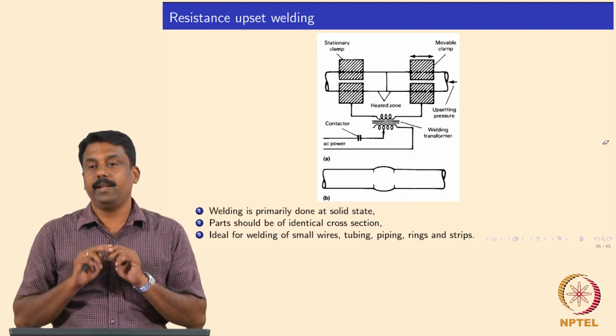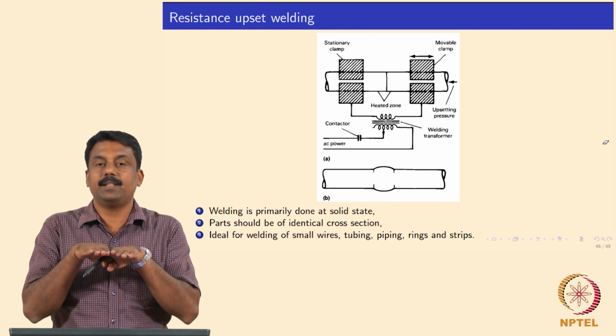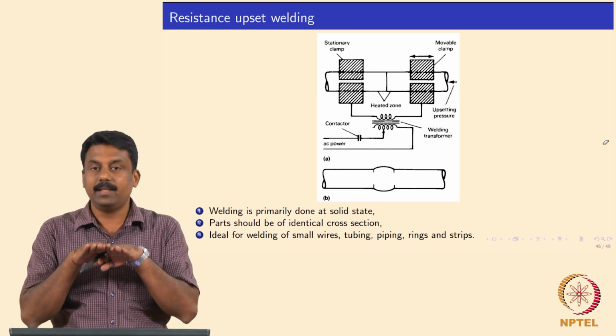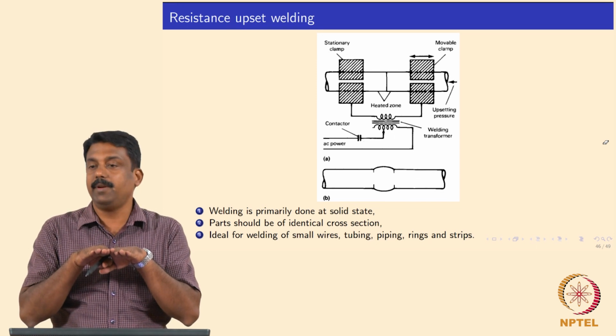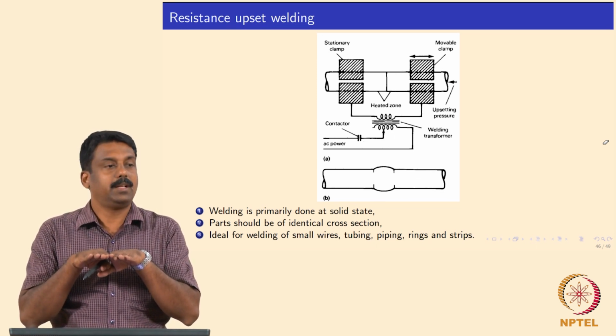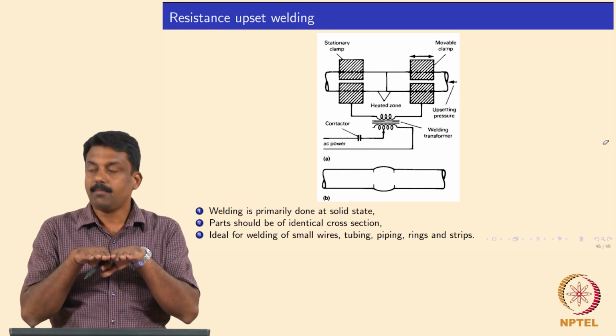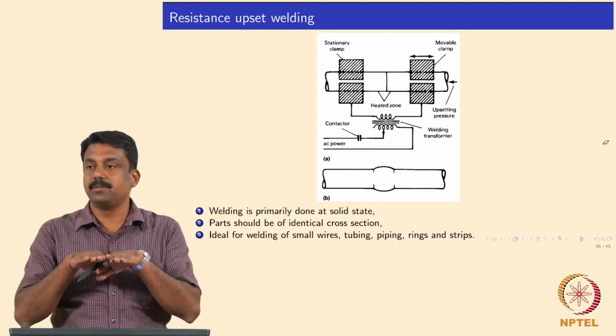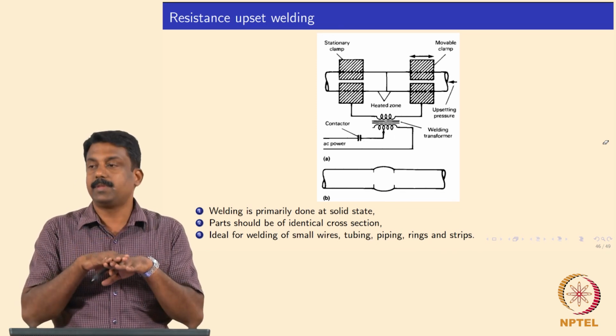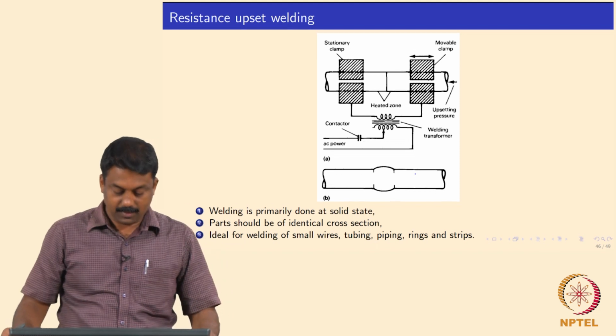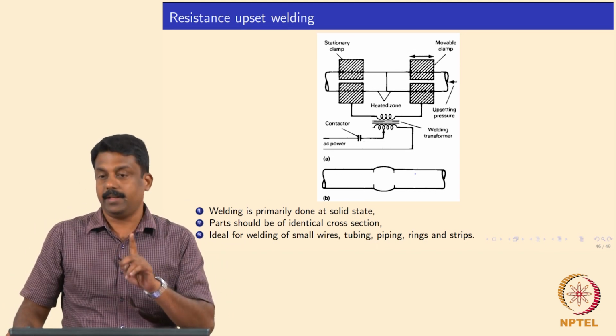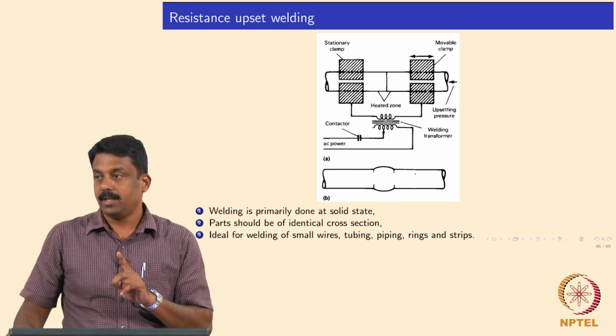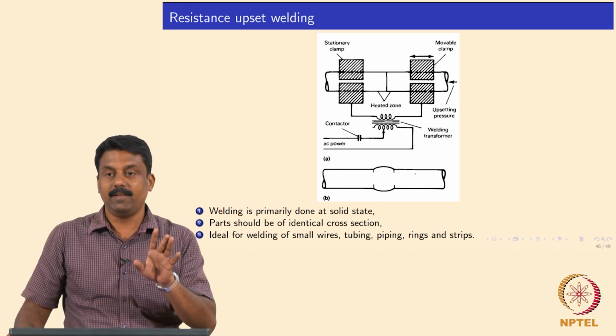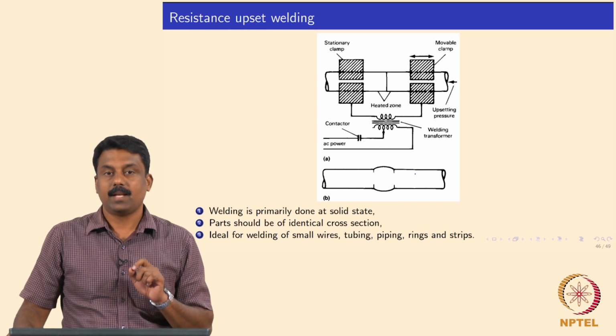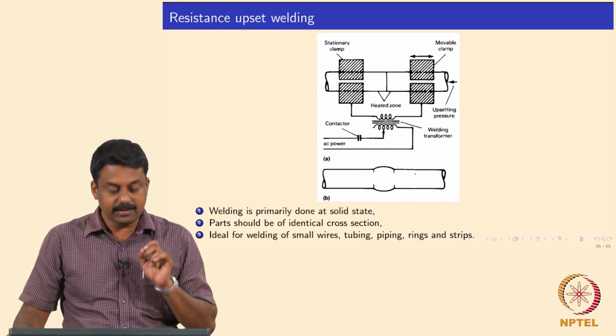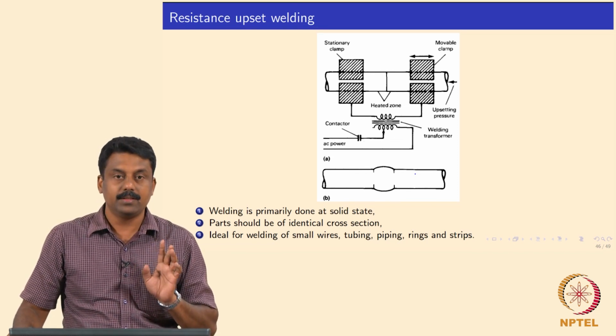Whereas in resistance upset welding, we keep the interfaces as close as possible, and then we heat it up, and we do not melt anything. We just heat it up, and the moment the temperature reaches a higher level, we do an upsetting to form a joint. So the welding is done in a solid state, there is no liquid involved in resistance upset welding. On the contrary, in flash butt welding you always have a liquid at the interface. It is clear. So in resistance upset welding the welding is primarily done in the solid state.